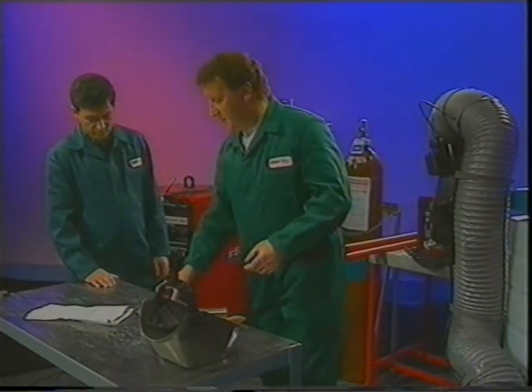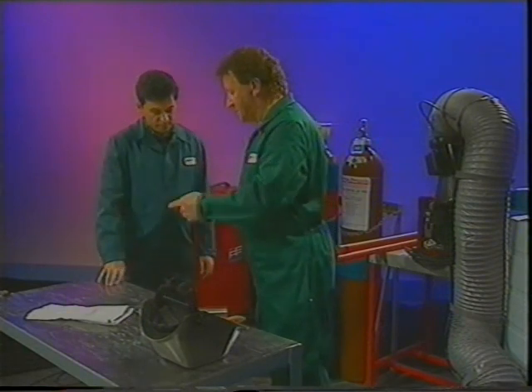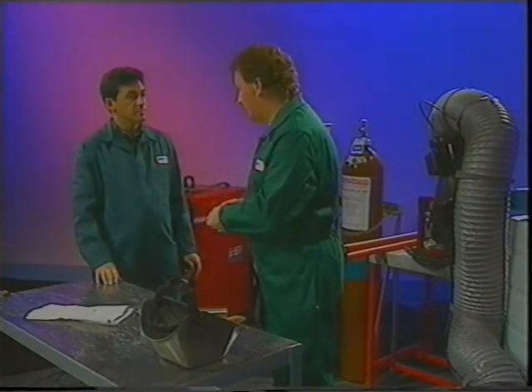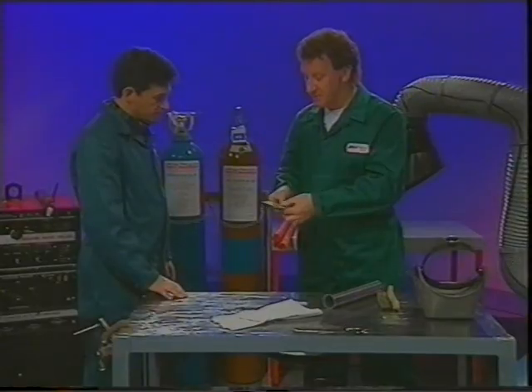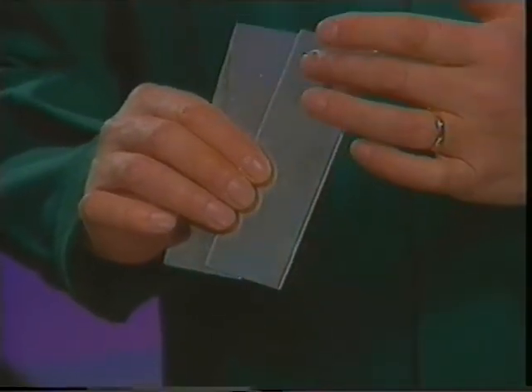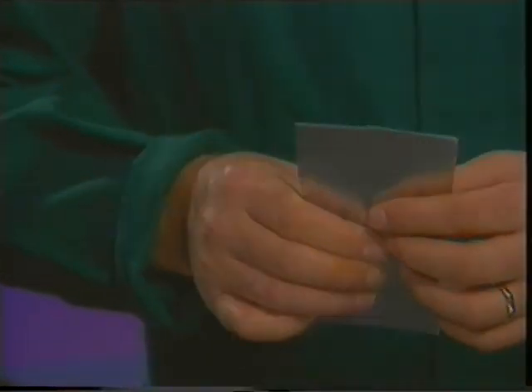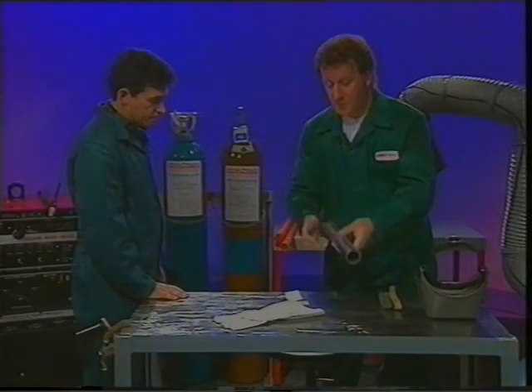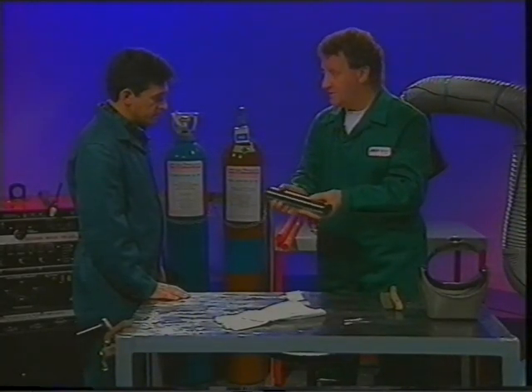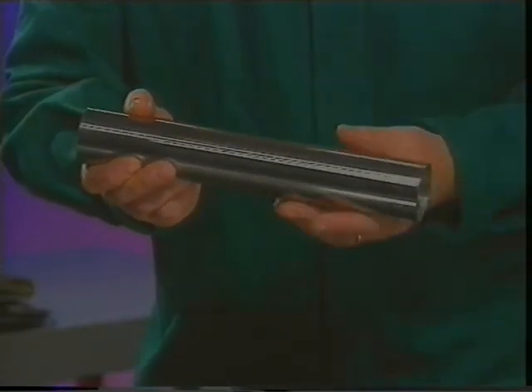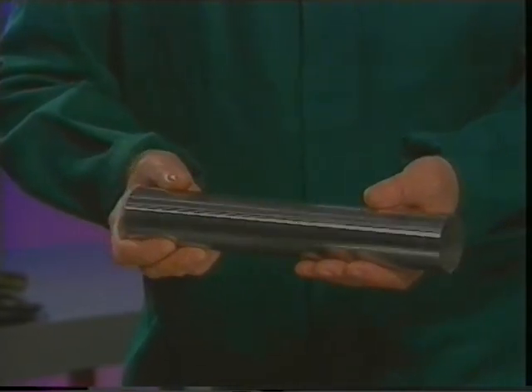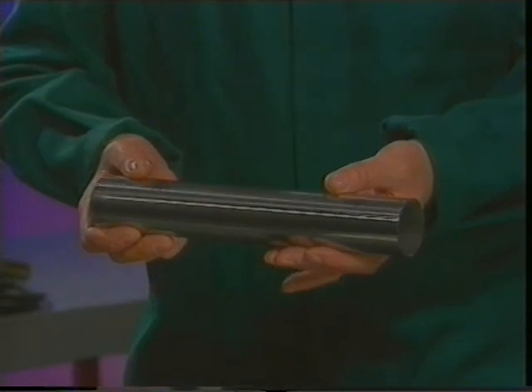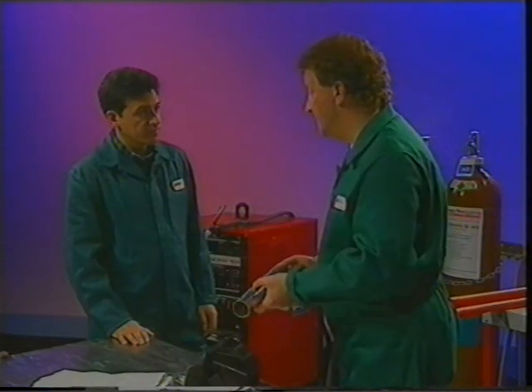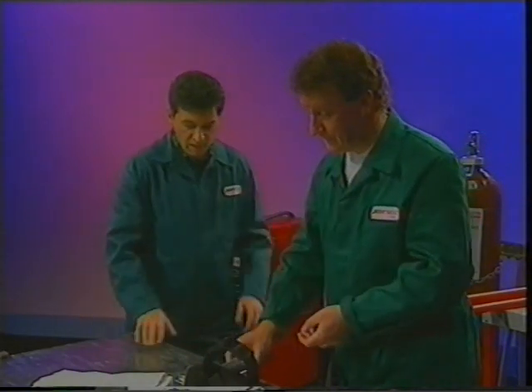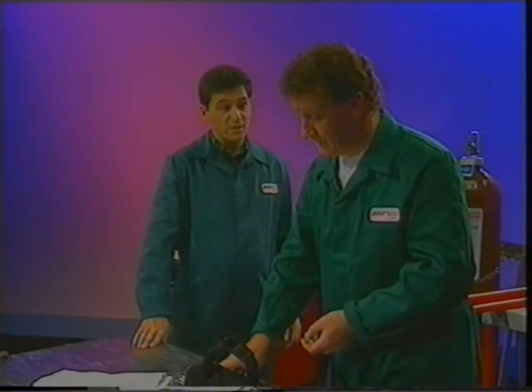Indeed, the surface of the weld where the torch has been is going to be well protected by the gas shield, and so will not have any oxidation. But the reverse side, particularly on stainless steel, will almost certainly have oxidation. This can lead to corrosion problems. With a pipe, we would fill the pipe with a purge gas, so that we have no corrosion problems on the back. This would be particularly important in the food industry, for example, where any corrosion can lead to microorganisms in the crevices. OK, so that's nice and clean and sterile as far as you can get it inside.